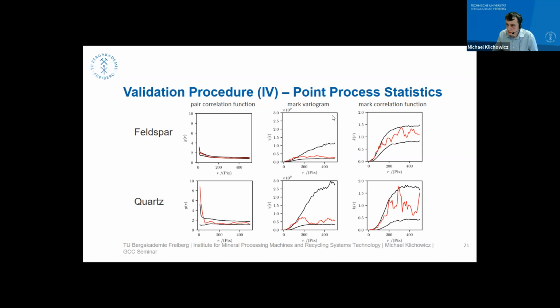The second measure is a so-called mark variogram, and it characterizes the similarities of marks. So marks are here the grain sizes, the grain areas, and it converges in the end to the variance of the marks, so to the variance of the grain sizes. But smaller values of this gamma indicate that we have similar mark sizes. So we have very small values for this measure at the beginning, which indicates that grains which are near or next to each other tend to have similar sizes.